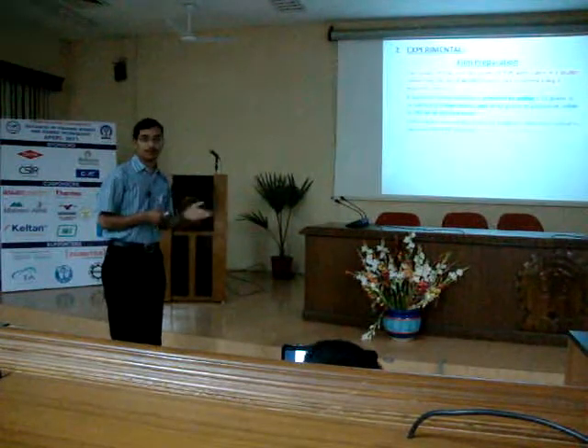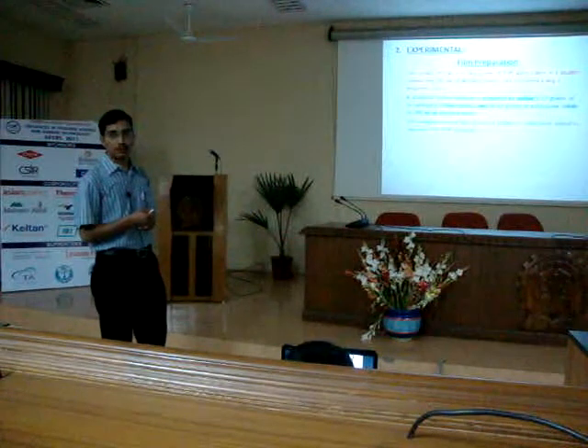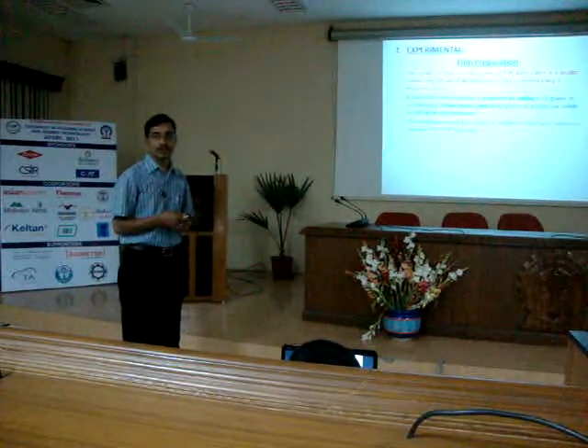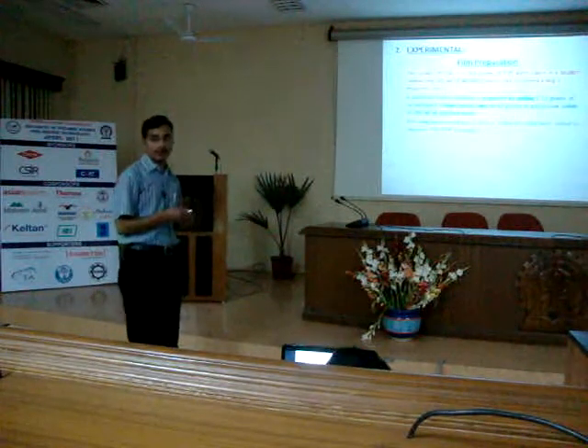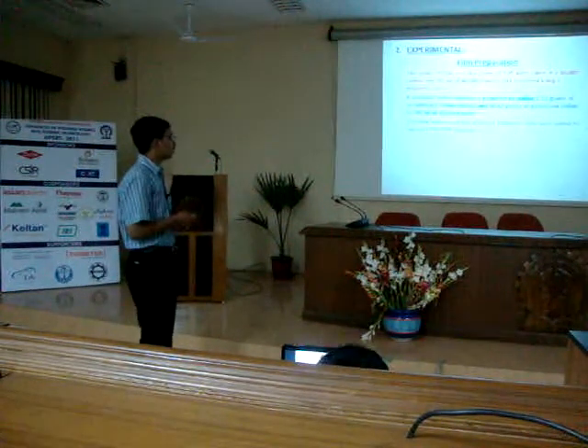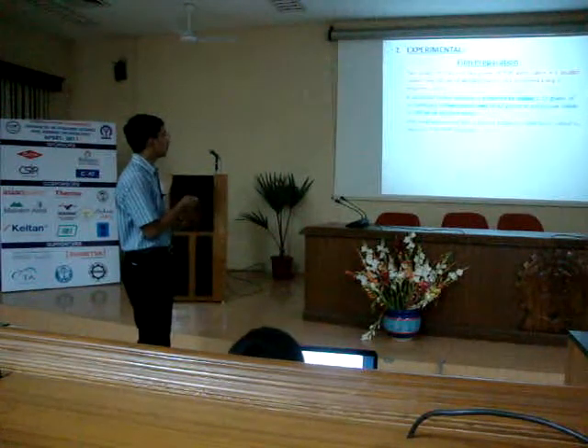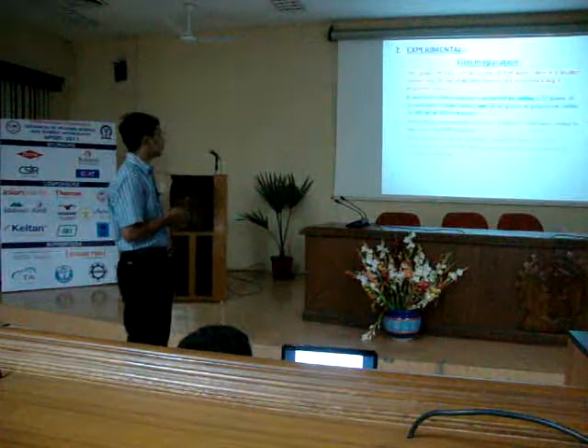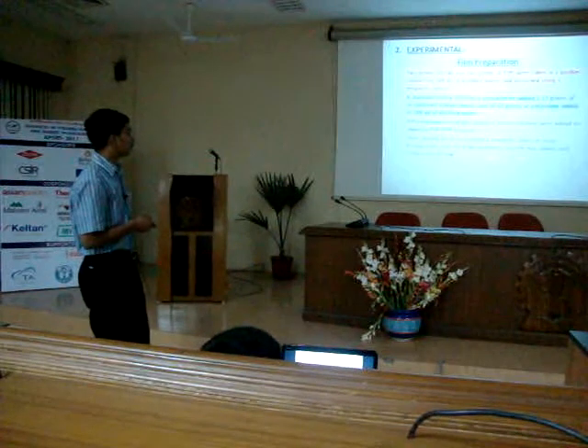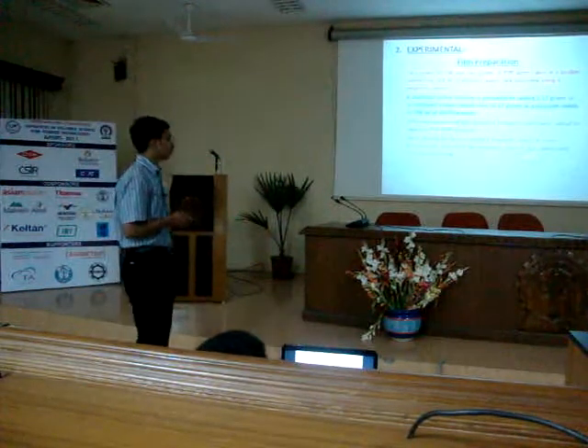So here, as I explained in the formula of doping level, that is 0.1794, it is obtained as 1.27 grams plus 16.67 grams divided by 100. So that gives 0.1794. And now different volumes of this standard iodine solution were added to the aqueous PVA PVP solution, which we prepared in the first part. Next, after stirring for an hour using a magnetic stirrer at room temperature, 2 ml of the monomer pyrrole was added with continuous stirring.